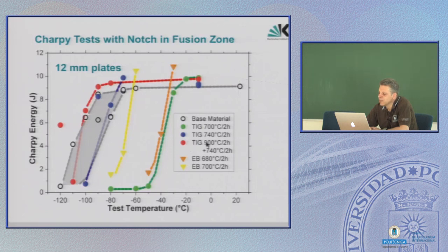Red means thick welded and a complete heat treatment with 900 C solution annealing and 740 C tempering. Well, you can use this for the production of these breather boxes, but it's not astonishing that here we have a full recovery of the weld. Blue, that's also very promising. Blue is also tungsten inert gas welding with only 740 tempering. That's still too high for the breather boxes.